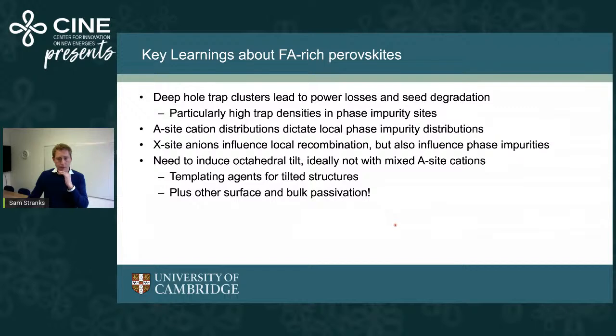So I just want to summarize now what we've understood from this. What we're seeing in these formamidinium-rich perovskites is that these deep hole trap clusters are traps for photo-excited holes in particular, and that leads to power losses and fuels degradation as well. This is particularly because these phase impurity sites have very high trap densities. So a lot of this redox chemistry is very problematic and much more active at these sites than in the more pristine sites. It looks like the A-site cation distributions dictate the distributions of these local phase impurities.